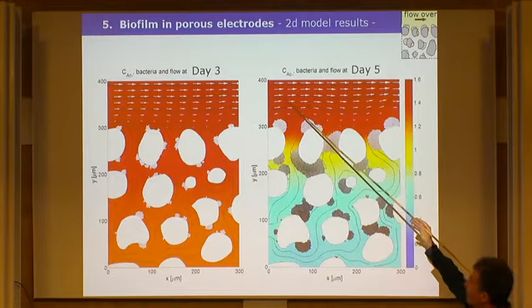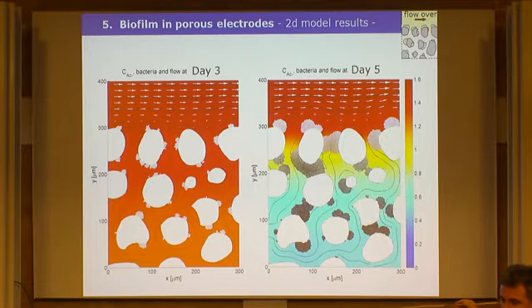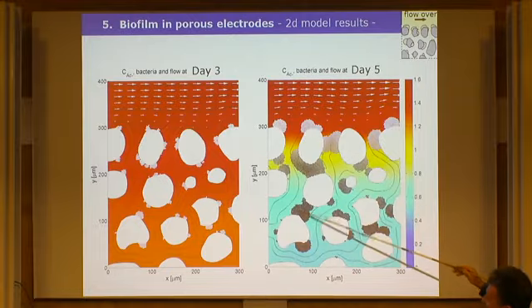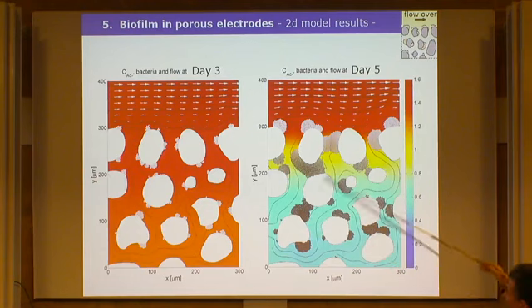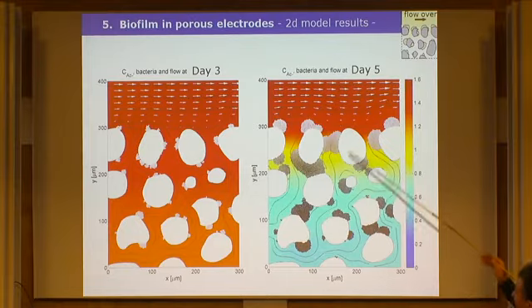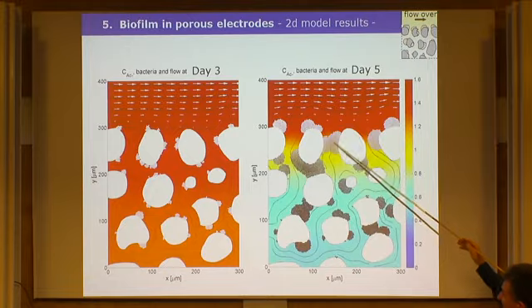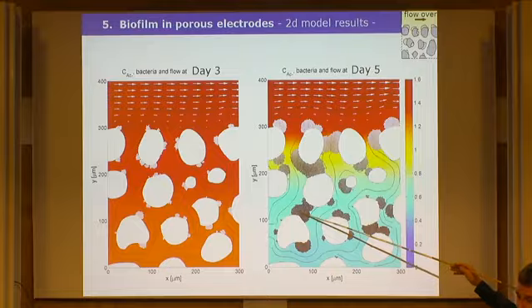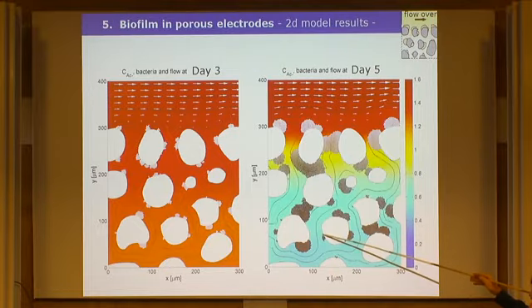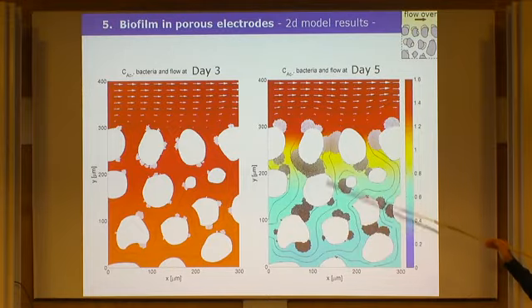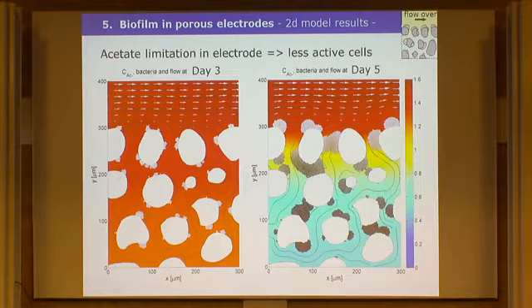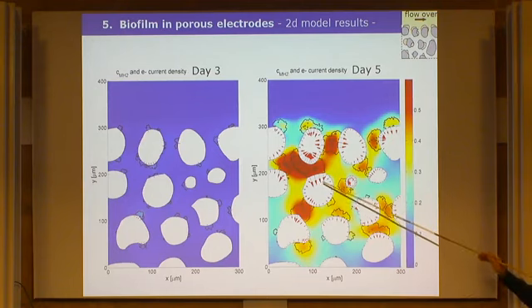So this is the surface, and there is a flow. These white arrows mean flow. Flow calculated here, and there is transport mainly by diffusion within the porous medium. And black means that the cells are suffering. I tried to put some meaningful color codes, at least in the Western culture. So white are active cells and black are less active or inactive cells, because there is much less acetate here. So practically these porous electrodes are good only if you are able to provide the substrate deep in this porous medium. And well, here you see also the electron currents going to the graphite beads.